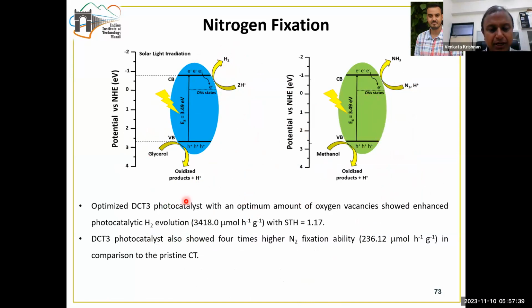We found that the photocatalytic hydrogen evolved is about 3418 micromole per hour per gram, with an STH, the solar-to-hydrogen conversion efficiency, of 1.17, which is not a great value, but nevertheless matches the current state-of-the-art values. Then we utilized the same catalyst for nitrogen fixation, the nitrogen to ammonia conversion, which gives a value of about 236.12 micromole per hour per gram, which is 4 times higher than the pristine calcium titanate.